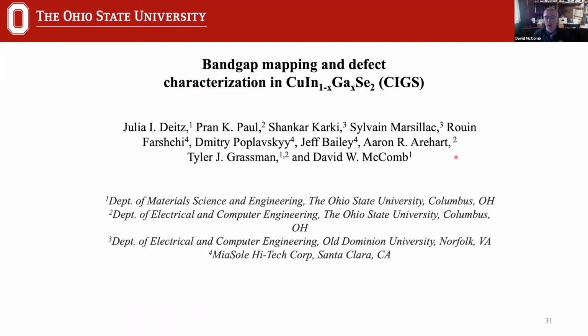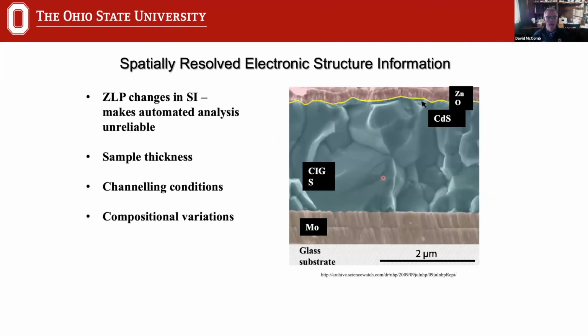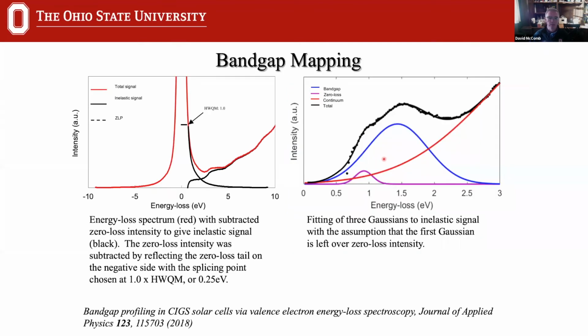Now, let me talk about a different aspect of using high energy resolution, and that's in inorganic photovoltaics. This is principally the work of Julia Dietz, who was co-supervised by myself and Tyler Grassman here at OSU. This is looking at copper indium gallium diselenide. Here our goal was to see what we could do in mapping over a pretty large device. This is a 2-micron scale bar. In this CIGS device, there are compositional gradients built into it in order to optimize the performance. And here, what we really wanted to do was map the band gap.